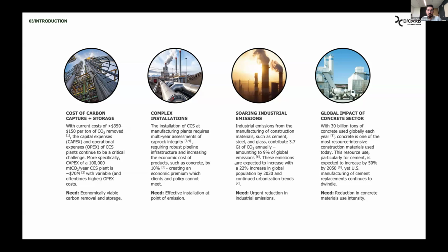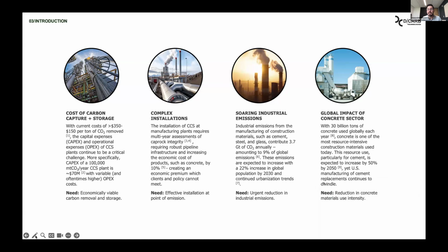When we look at concrete specifically, 30 billion tons of concrete used globally each year also means that concrete is the most resource-intensive material in the world. And we're going to talk a lot more about resource intensity, because when we look at cement, that intensity is only going to increase, and it's going to increase by 50%, the estimates are, by 2050. Yet when we look at cement replacements, such as fly ash, for example, those have continued to decrease over the past 2 decades, which creates a real need for reducing the resource use intensity of concrete or using less cement, which is mainly what it comes down to sometimes.